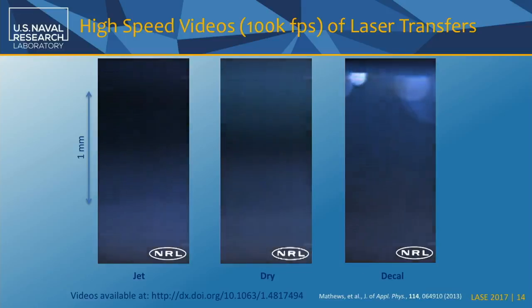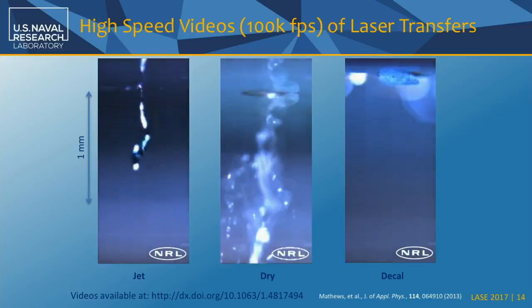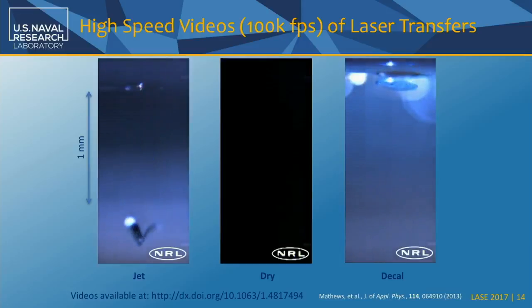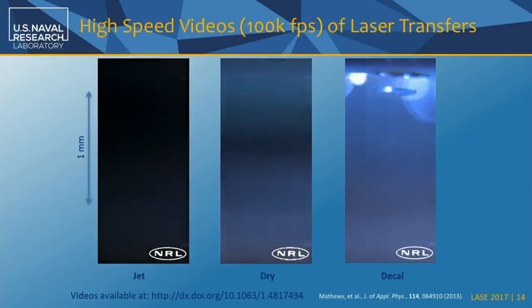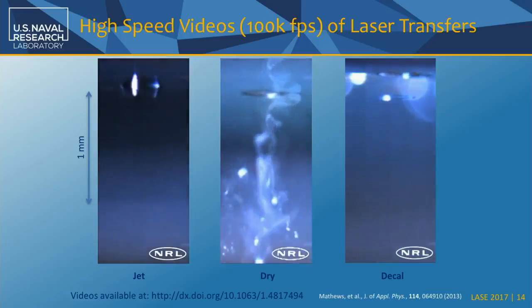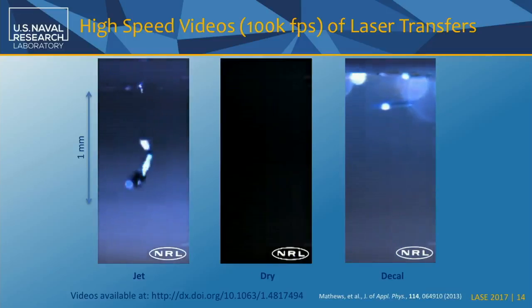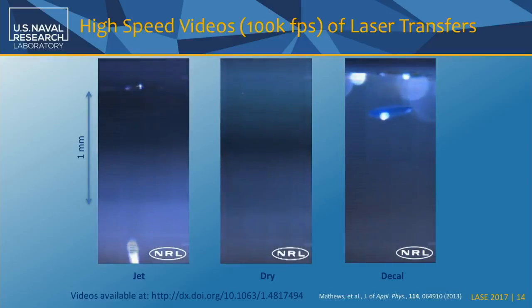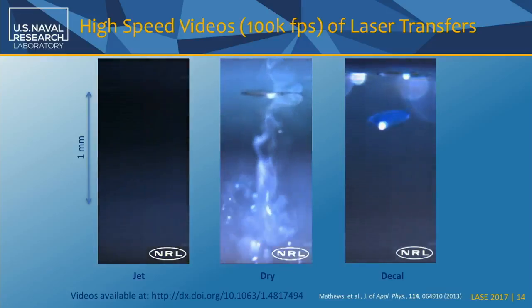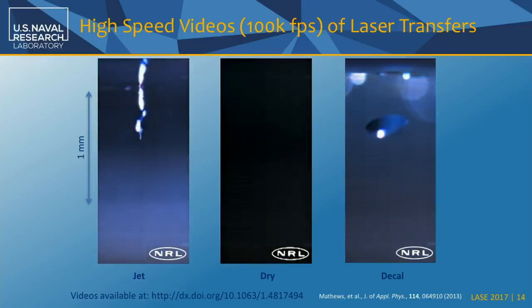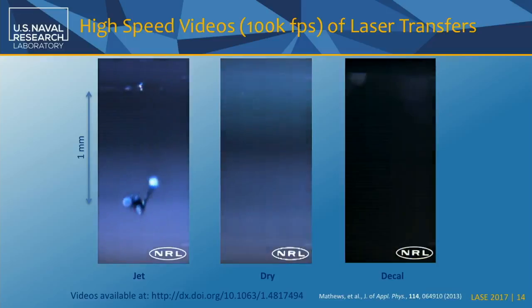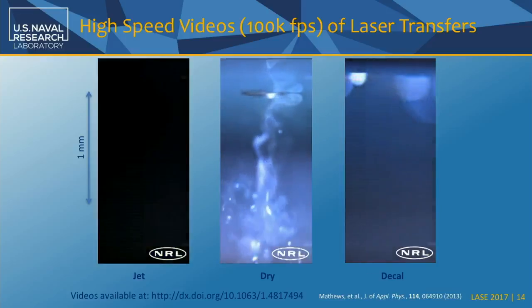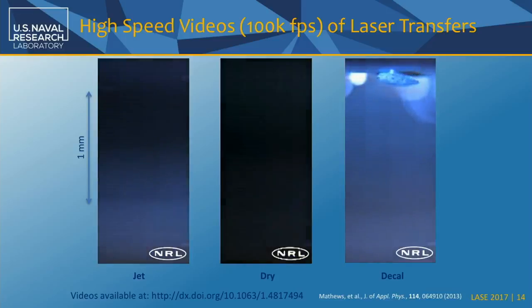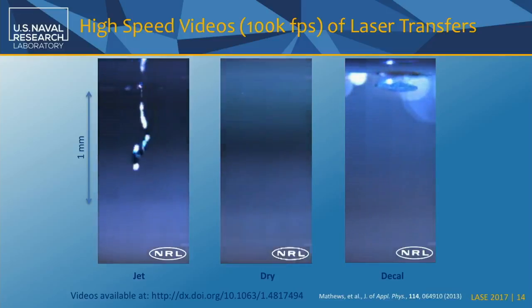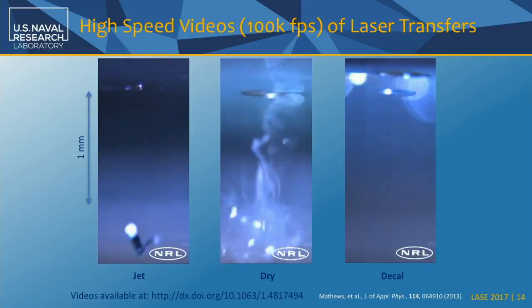So if I play these videos, what you're going to notice is first the illumination from the laser pulse. The laser pulse is hitting right at this point here. This is the interface between the donor substrate and the ink. And you notice that we have actually 3 different regimes. You can see that the dry transfer is completed while what we call a decal transfer, or this congruent transfer that I mentioned before, is still going on. And the videos are repeating so you can see it again. And here is the jet formation and a drop, just being ejected.